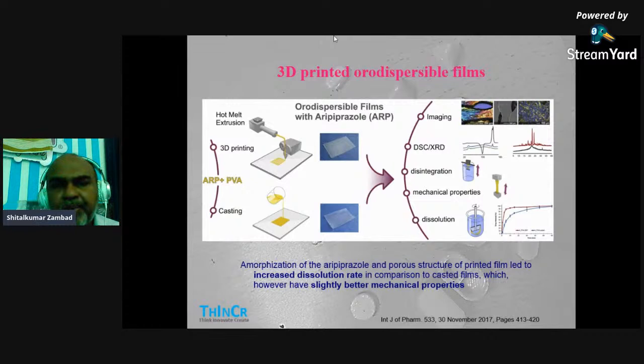orodispersible film of aripiprazole, there is an amorphization of the aripiprazole, and the porous structure of the printed film leads to an increased dissolution rate. So the drug release was higher in the 3D printed film due to its porous structure and the amorphization of the aripiprazole.